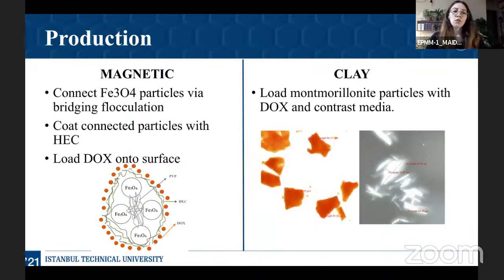Okay, I will explain our production methods here. If you can see my mouse, we linked these nano-iron oxide particles together via bridging flocculation using a polyvinylpyrrolidone polymer. Later on, we coated the outer surface with another polymer, hydroxyethyl cellulose. Finally, we loaded doxorubicin, which is an anti-tumor drug, onto the surface. If we move on to the clay mineral particles, we use bentonite here. We loaded bentonite with doxorubicin and X-ray contrast media via the adsorption method.